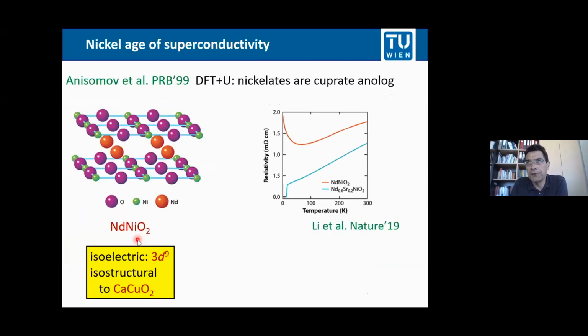As you all know, two years ago, there was a great breakthrough in condensed matter physics. Danfeng Li and co-workers from the Hwang group at Stanford discovered superconductivity in nickelates. Here is a picture of the graph of their original publication, resistivity versus temperature. For the undoped nickelate, neodymium nickel O2, you have a bad metal behavior at high temperature and a weakly insulating behavior at low temperature. But if you dope it with 20% strontium, you get a superconducting transition at 15 Kelvin.